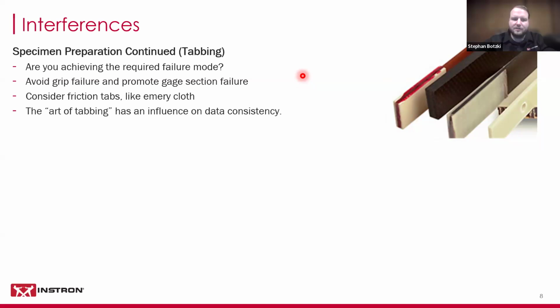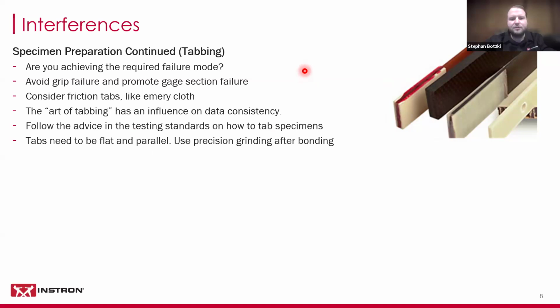And tabbing itself in general is kind of an art, and it definitely can have an influence on your testing data, on the consistency of your data. So just like the specimen preparation itself, where you machine the coupon, you need to take the same care with your tabs and also follow the tolerances within the testing standards. So that's what you should do when you look at how to tab, what kind of tolerances to follow. And you also need to make sure they're flat and parallel. You use precision grinding methods after they've been bonded. And typical materials that we see used are glass fiber reinforced plastics bonded to typical CFRP coupons. I've seen different types of metals like steel or aluminum. And I've also seen in testing standards that they actually recommend using the same material that is being tested as tabs as well.